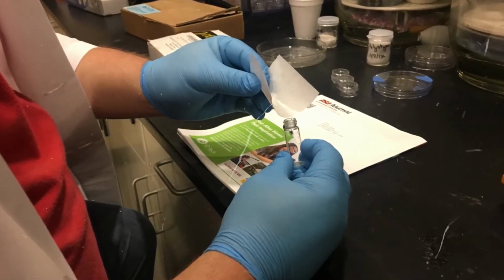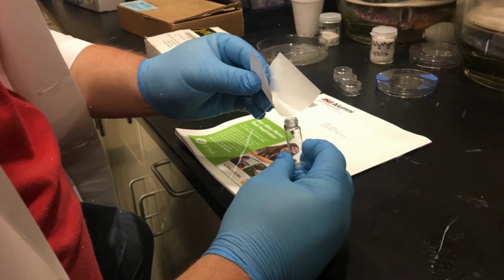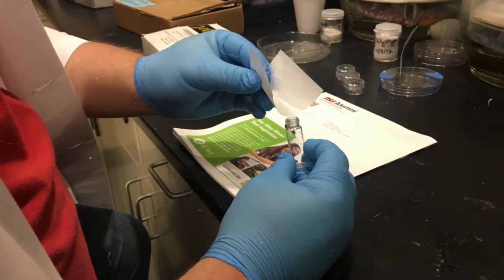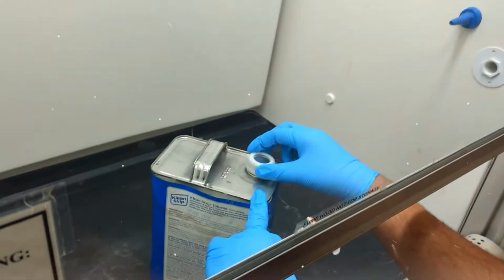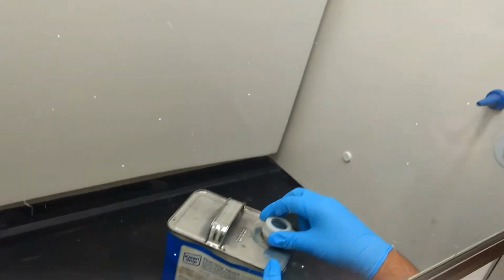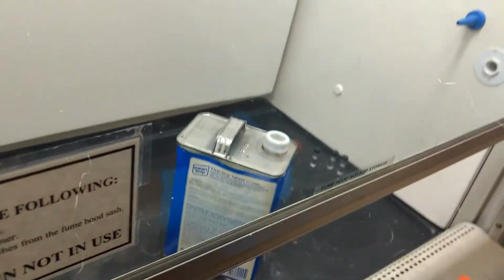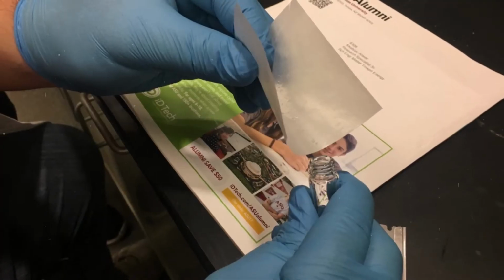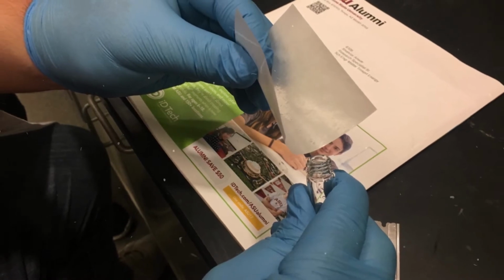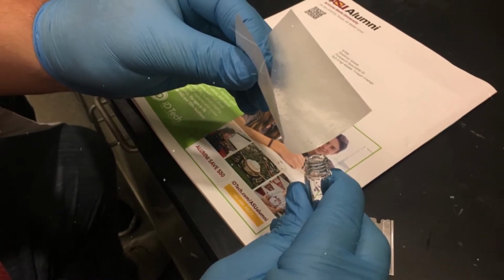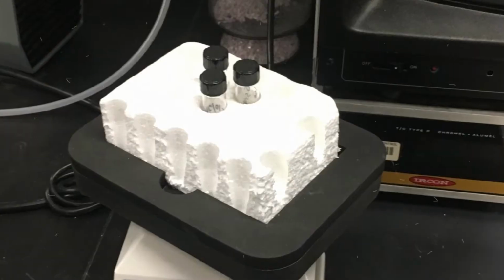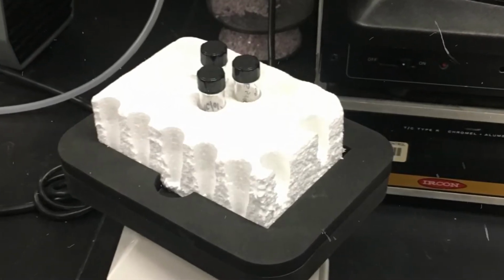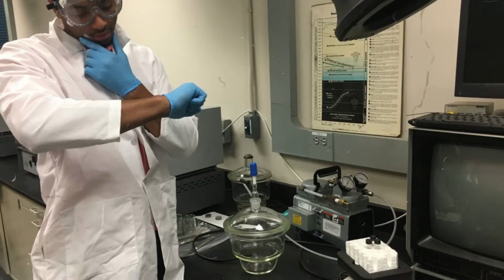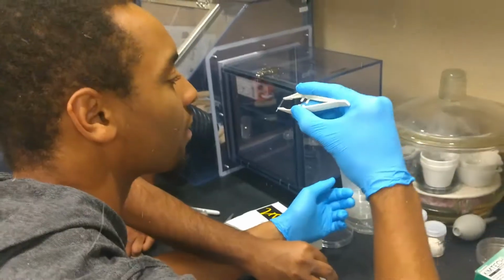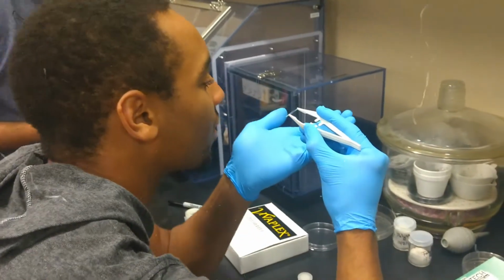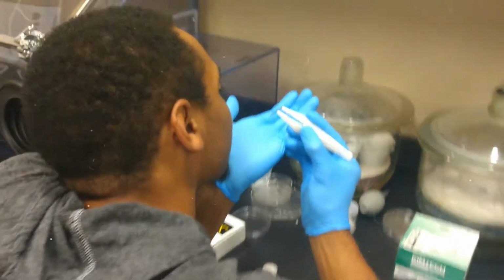First, the polystyrene pellets must be crushed or chopped to maximize the surface area to allow for faster dissolution. The volume of toluene is measured with great care, taken to ensure the precise amount is added to the vial. After the polystyrene is chopped, it is added to the toluene in the vials. Next, we take the vials to the vortexer to speed up the dissolution even more. One eternity later. Now that the polystyrene is thoroughly dissolved, the samples are prepared for spin coating.